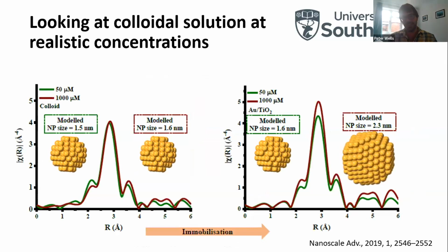And what this did was it allowed us to decouple the properties of the colloid in solution at different concentrations and the properties of the colloid once it was immobilized onto a titanium support. And what we found was that we could change the concentration of the colloid in solution from 50 to 1,000 micromolar, and the EXAFS data, statistically, was essentially identical. There was no change.